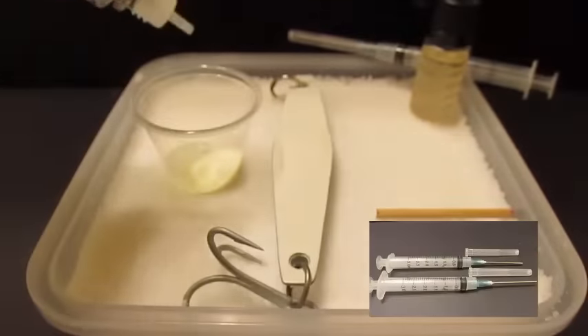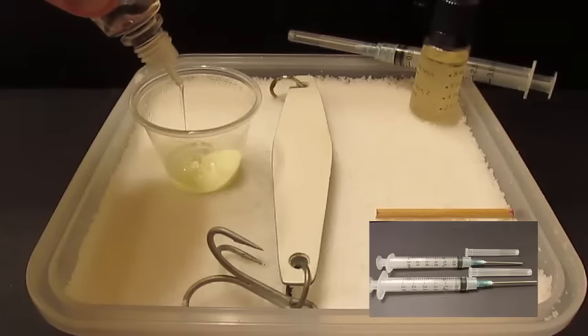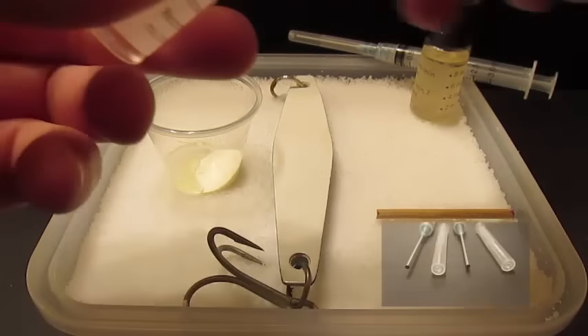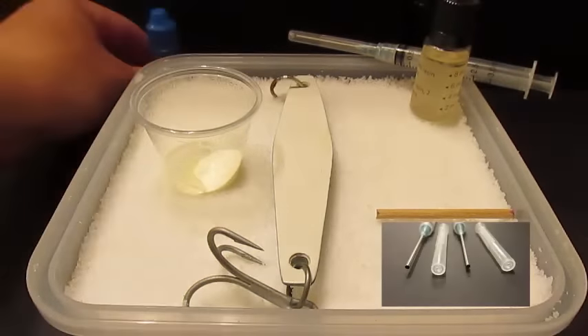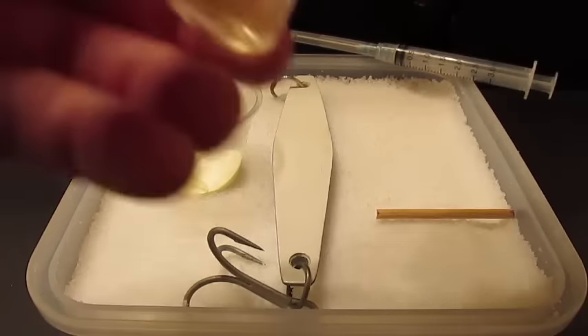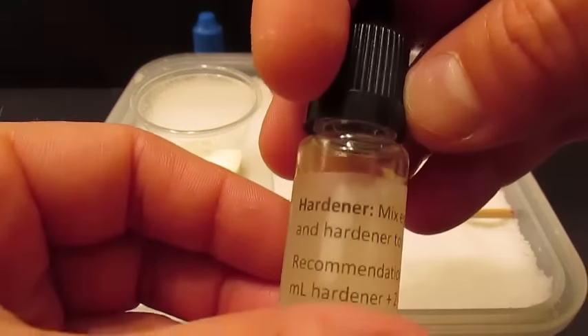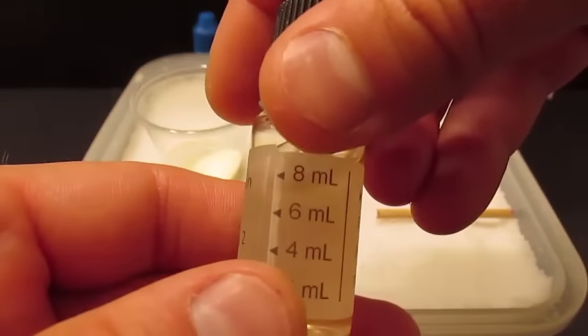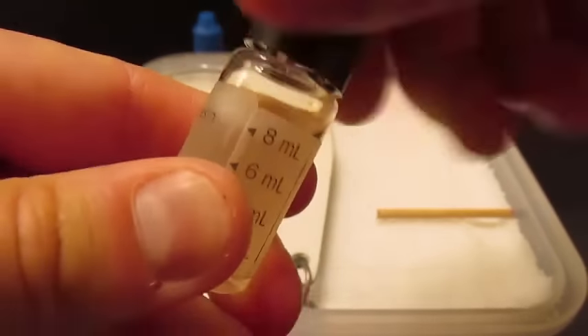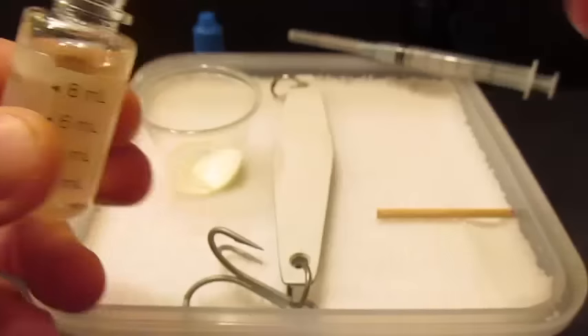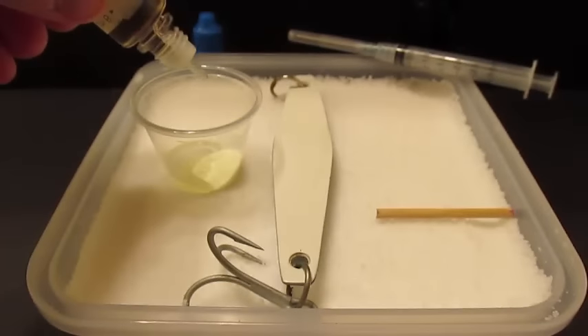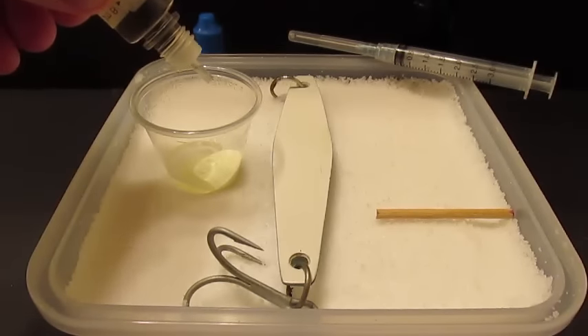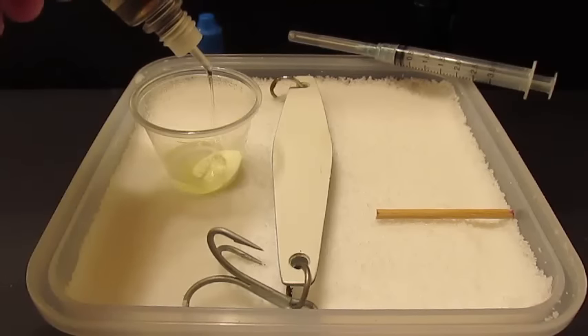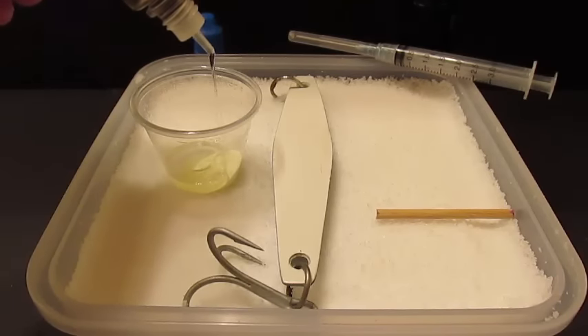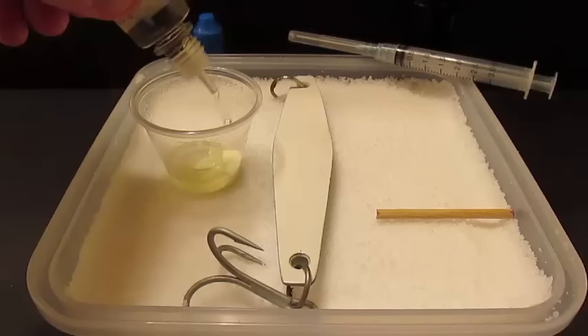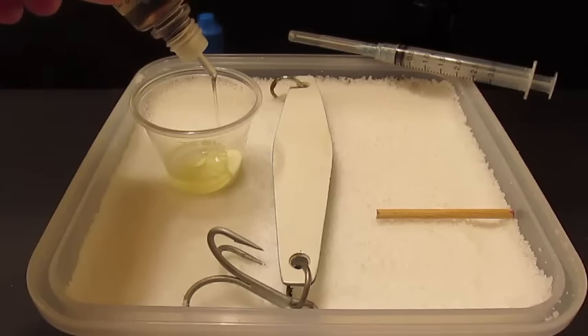Now, you can use more or less pigment depending on how much of a glow effect you want or how you want to control the rate of self-leveling with this material. But whatever you choose, you have to use a 1-to-1 ratio of resin to hardener, which you see me measuring out here. Any other ratio that's not 1-to-1 will result in the coating not curing, so measure carefully. Again, in this video, I'm using 2 mLs of resin and 2 mLs of hardener to get that 1-to-1 ratio.